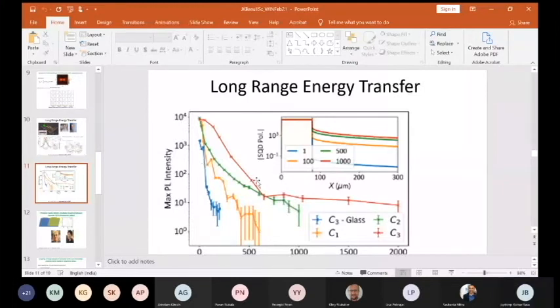What we observed, interestingly, is that the red line here is the one with the highest concentration. Remember that this is concentration-dependent strong coupling. The strong coupling goes up to even 100 meV. If you increase the strong coupling, the length of this propagation increases. So there is a scaling. This is the lowest concentration, this intermediate one, and this is the longer one. As you increase the concentration, you increase the magnitude of the coupling, and you also increase the ability for these modes to propagate.